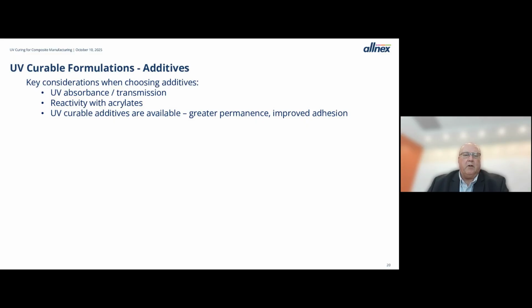Additives, as I mentioned, we're not going to talk about too much, except to say when you're looking at additives for a UV system, make sure you understand if they absorb in the UV or not, if they're going to interfere with the photoinitiator trying to grab that UV energy from the lamp, whether they're reactive with acrylates, whether they're compatible with acrylates. And finally, there's a lot of areas in composites where you don't want fugitive materials. And so there are UV curable additives that will react into your polymer matrix for greater permanence and won't be extractable. So just some things to think about when you're looking for additives.